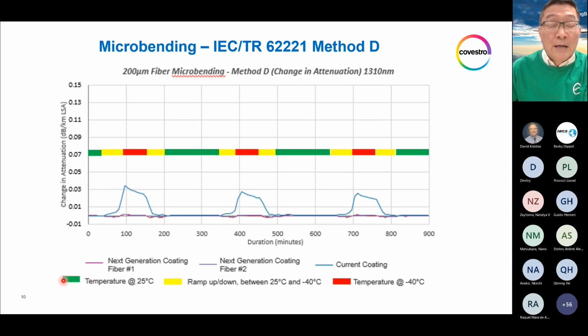The temperature was color-coded green, which means the cycle starts at 25 degrees C, which is ambient temperature. Then we gradually reduce the temperature all the way to minus 40 degrees C over about 1 hour. Then the fiber is kept at minus 40 degrees C for about 1 hour again, 60 minutes. Then we gradually ramp up the temperature from minus 40 back to 25 C. So the cycle is from 25 to minus 40 to 25 again.